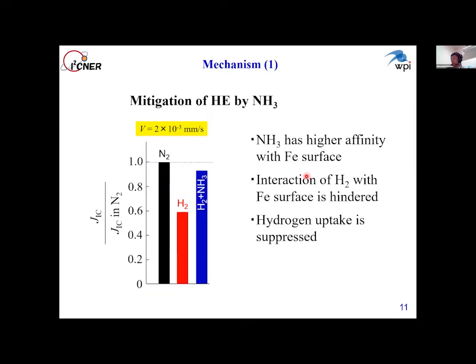Regarding the mechanism that NH3 mitigated the hydrogen embrittlement, we already confirmed the NH3 has higher affinity with Fe surface. Adsorption of NH3 on the Fe surface hindered the interaction between hydrogen and Fe surface. As a result, hydrogen uptake is suppressed. Eventually, hydrogen embrittlement was mitigated.